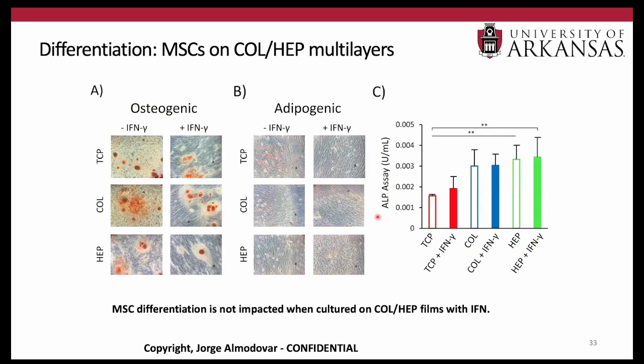We wanted to make sure that our surfaces don't affect the differentiation of these cells, and so we went ahead and differentiated them toward the osteogenic and adipogenic lineages. We used different stainings, alizarin red and oil red O, and basically all of these images show you that the cells have the capacity to differentiate. We did another assay, an alkaline phosphatase assay, showing that, again, the cells can go towards the osteogenic lineage. Another important function of the MSCs is their capacity to differentiate, and lo and behold, they can still do that.